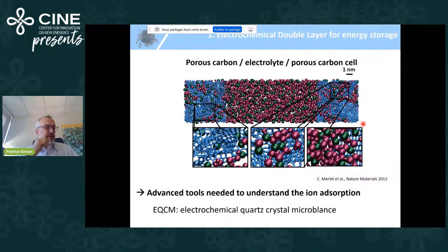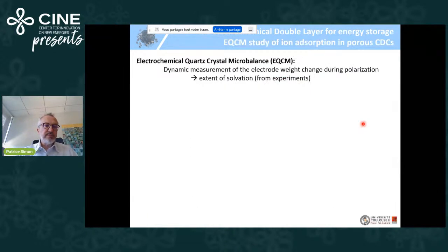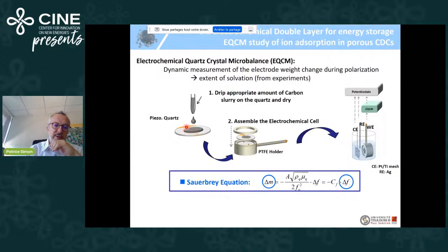I'm going to show you examples of the first technique we are using, which is EQCM, electrochemical quartz crystal microbalance. The idea is to try to have an experimental confirmation of desolvation of ions when entering small pore size. So what you do is that you take a piezoelectric quartz with a resonance frequency, and you coat this quartz with porous carbon mixed with a binder. Then you use this quartz as a working electrode in a conventional three-electrode cell. And during the experiment, you polarize your material positively, negatively, and you record the change of the quartz resonance frequency.